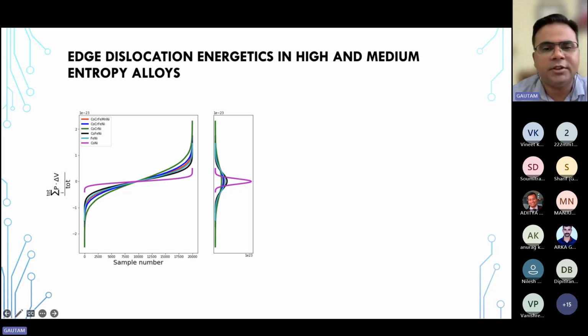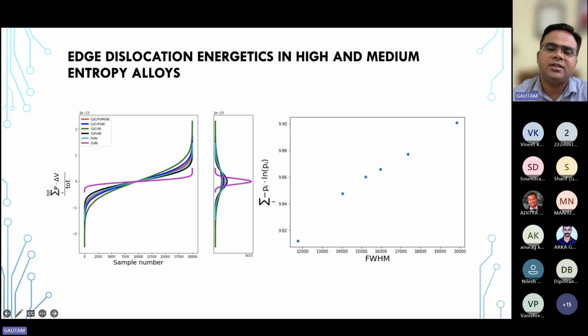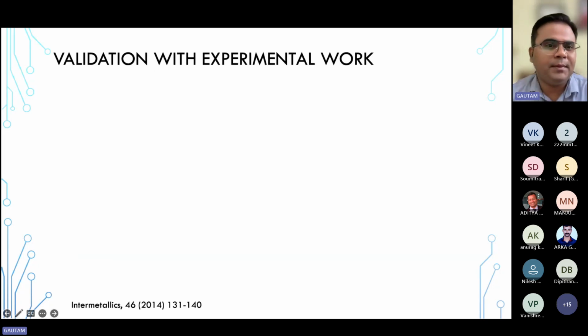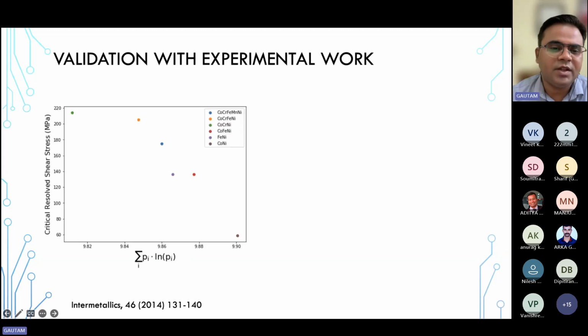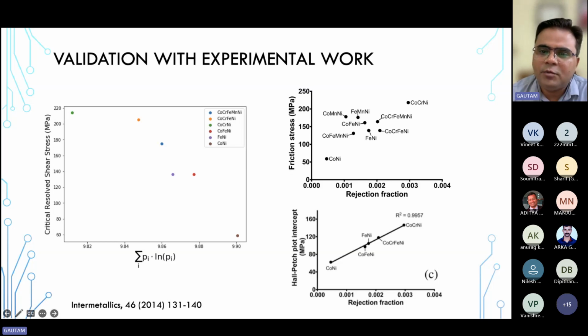Now we are talking about the energetic terms, and the full width half maximum of this distribution of energies has a linear correlation with the entropy parameter which we just talked about. So can this entropy parameter make some prediction about the strength? We compared this with some experimental results, and as you can see, it shows some correlation with the critical resolved shear stress. Obviously, strength is a complicated parameter to predict, and we're talking about a Cantor alloy with some complicated elements such as manganese. For most of the cases we're getting a linear correlation, but particularly the elements having manganese seem not to come in line, and this is visible here also.